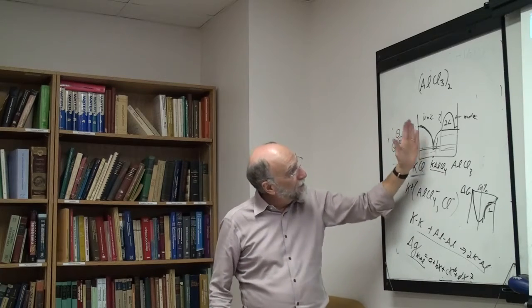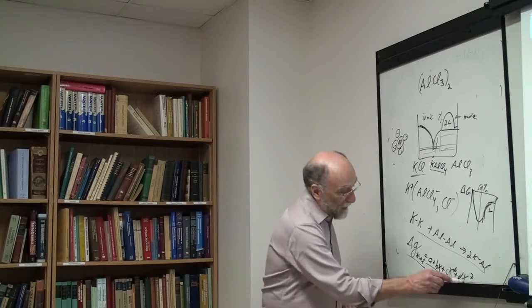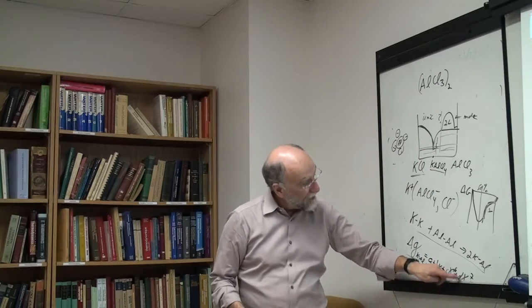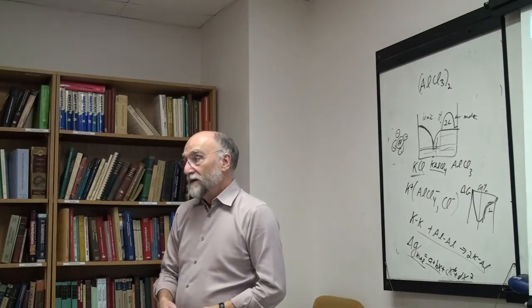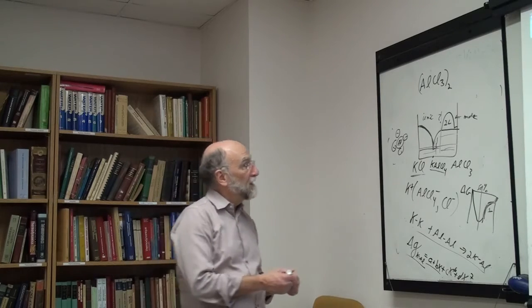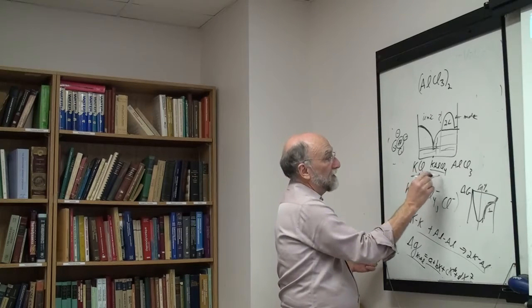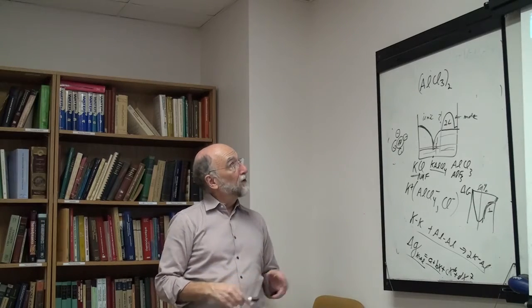You want to fit the left side of the diagram, which usually can be fitted with one or two parameters simply, and then you want to add parameters over here to give you this blip. But you don't want to start playing with these numbers and having to constantly change what's going on here. So in these cases, we find that these powers are better. So this is what happens with aluminum chloride. Similarly with aluminum fluoride, if you just replace this by fluoride, say sodium, if you put sodium fluoride and AlF3, then you've got cryolite, the bath for the aluminum Hall-Héroult process.